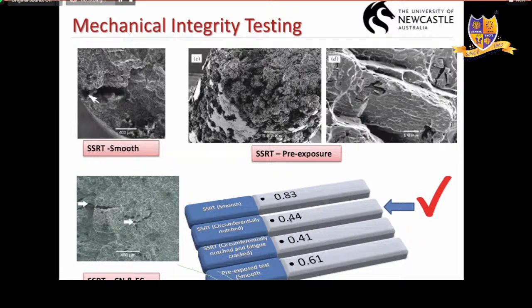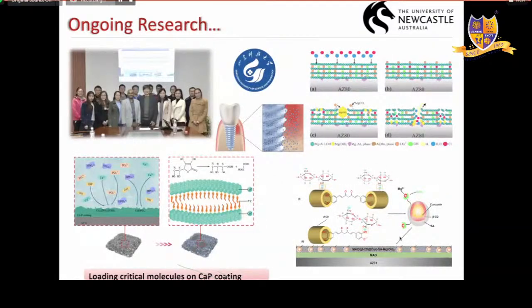So this circumferentially notched sample is better. Ideally we would like a fatigue crack, but it's much more expensive to do that. So we propose that the circumferential notch is the best sample. And there is some ongoing research.